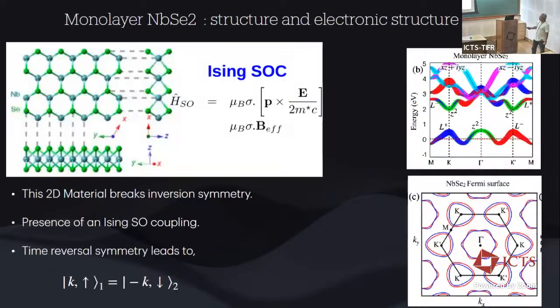Okay, to start off the story of monolayer NbSe2, if you have not been following the literature so closely in the last few years, what made this material interesting compared to the bulk version? The bulk version is a well-known conventional s-wave superconductor driven by an electron-phonon mediated pairing mechanism. For the monolayer system, however, when you go to this limit, what happens is that in the niobium lattice you have out here, the seleniums are sitting in a position so that for every position R, there is not an equivalent selenium at the minus R position.